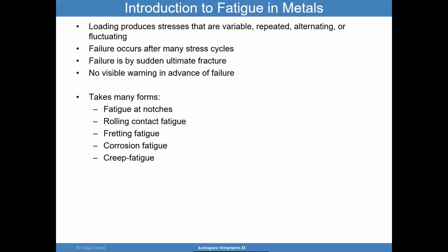So what are the loadings that can produce stresses that are variable, repeated, alternating, or fluctuating? There could be a lot of different sources, such as vibration, statically applied loading, for example, an aircraft that takes off and lands will see a ground to air cycle. And you can see there that the fuselage will get pressurized and then depressurized when the aircraft lands. Failure there occurs after many stress cycles. Failure is by sudden ultimate fracture. There's no visible warning in advance of the failure, and it can take many forms, like fatigue at notches. We see these kinds of fatigue failures in rolling contact fatigue. So if you have a ball bearing, you could have either fracture of the bearing or the cage that holds the bearing. We have fretting fatigue, corrosion fatigue, and creep fatigue.